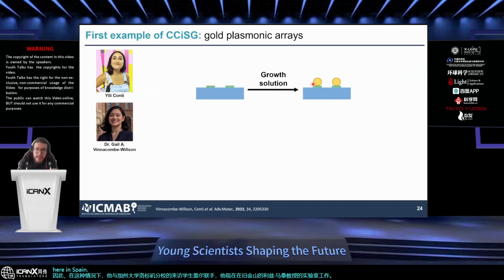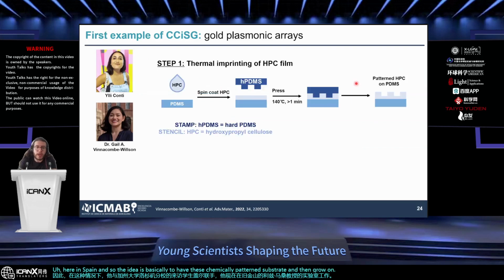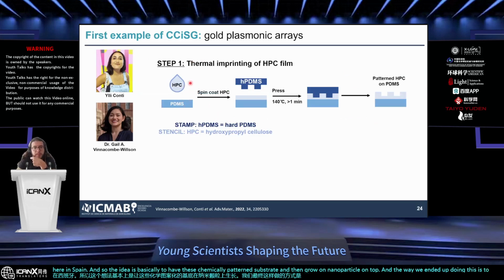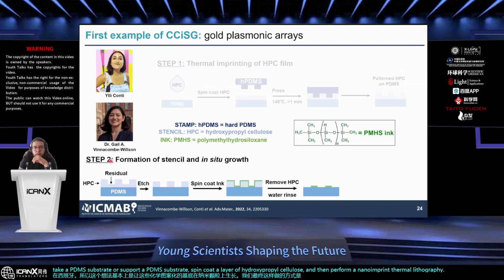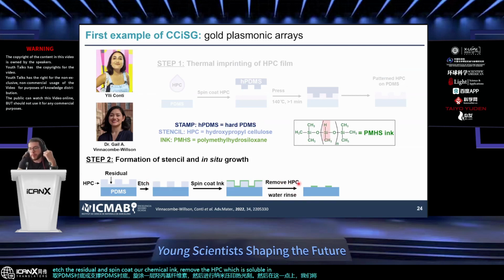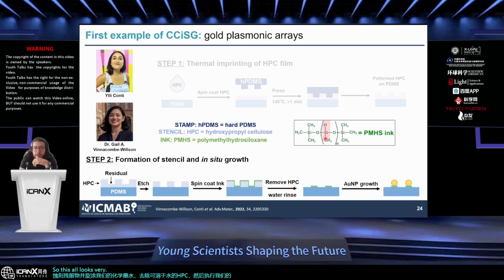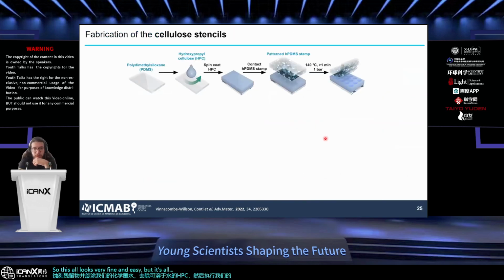And so the idea is basically to have these chemically patterned substrates and then grow our nanoparticle on top. The way we ended up doing this is to take a PDMS substrate or supported PDMS substrate, spin coat a layer of hydroxypropyl cellulose, and then perform nanoimprint thermal lithography. Then at this point, we will etch the residual and spin coat our chemical ink, remove the HPC, which is soluble in water, and then perform our growth. So this all looks very fine and easy, but of course it's not as easy as it looks.